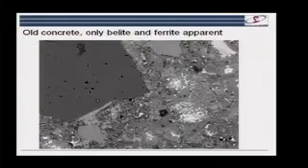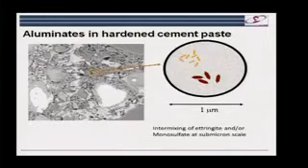Now, we've seen a lot of this kind of outer product. And you see in all these micrographs here, it's a jumbled up mess. It's very variable, but it's also a very finely intermixed material. So here's a kind of schematic zoom of one of these areas of this undifferentiated outer product. And on this fine level, we have CSH, which is represented by this background here, and within the CSH, we have little tiny crystals of either ettringite or monosulfate intermixed at the submicron scale.